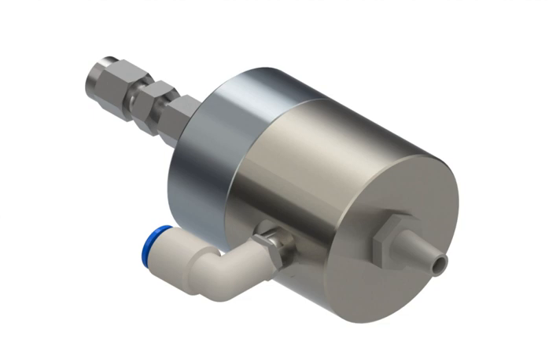The non-clogging nature of ultrasonic nozzles, the small and uniform droplet size created by them, and the fact that the spray plume can be shaped by tightly controlled air shaping devices make the application quite successful in wave soldering processes. The viscosity of nearly all fluxes on the market fits well within the capabilities of the technology. In soldering, no-clean flux is highly preferred, but if excessive quantities are applied, the process will result in corrosive residues on the bottom of the circuit assembly.